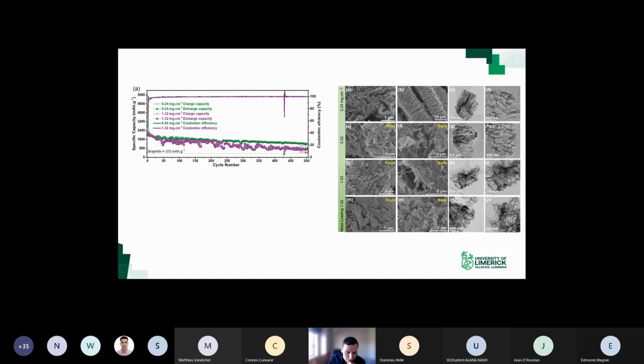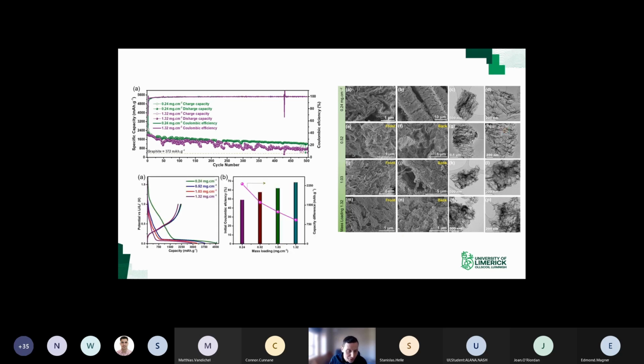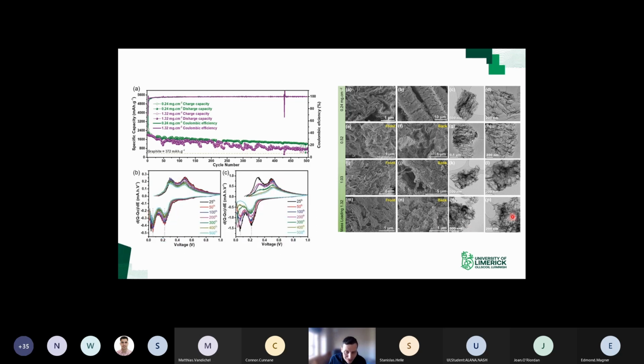We did post-mortem analysis of these, and we saw that the interconnected structure did form. I'll skip over some of these a little bit, but what was encouraging was that the morphology of the nanowires wasn't at fault here. The morphology of the active material wasn't the problem. What we think is that SEI layer thickening caused the higher mass loading one to degrade a little bit more quickly than the lower mass loading one. Evidence of that was a shift in the differential capacity plot peaks to lower potentials.